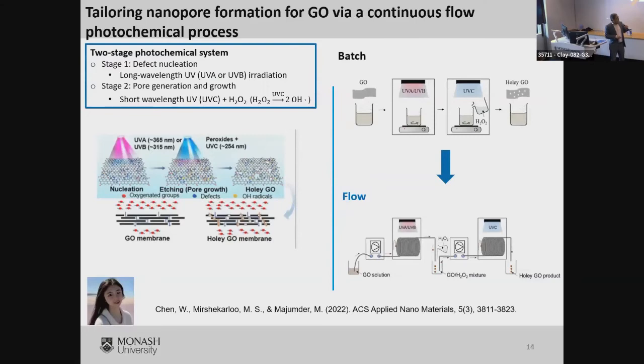From these learnings, Wanqing started to play around and see if we could harness this understanding into production and modification of 2D materials. So she found out that at a long wavelength, you can irradiate graphene oxide or even graphene, and you can nucleate defects. All right, and then subsequently you can use UVC, a shorter wavelength, and peroxide to etch. Okay, and the advantage of this two-stage process is that we can, number one, control the pore size, and number two, control the amount of porosity you have in the holey graphene. I think that's quite an exciting development for us.